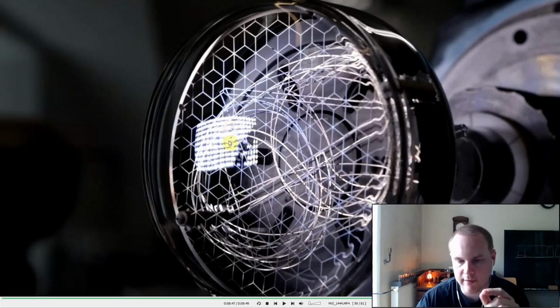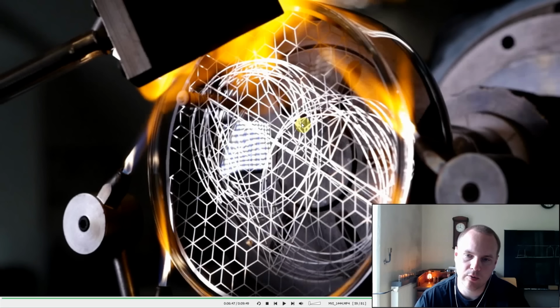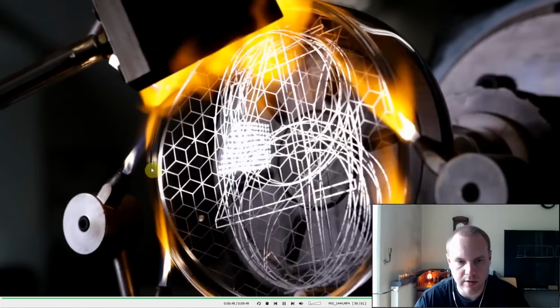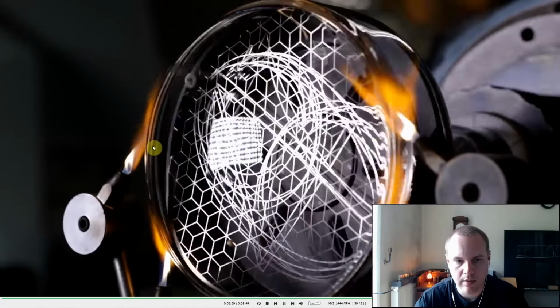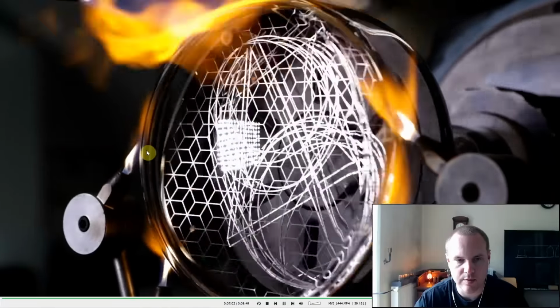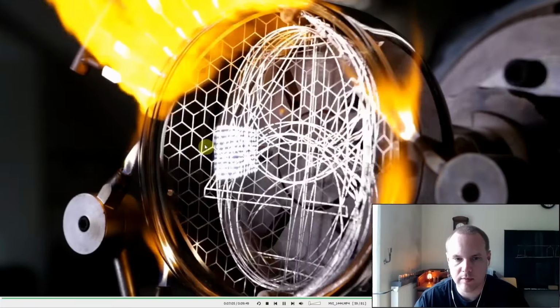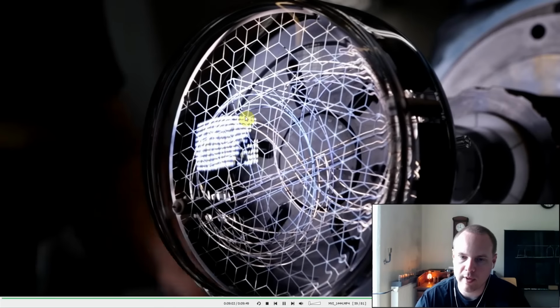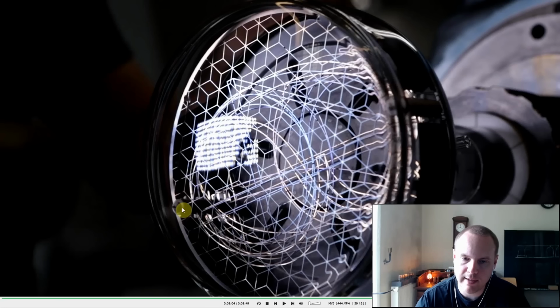The problem is that we didn't have the purging gas on during the annealing process, so the gas which is escaping from the torch could enter the tube and react with the digits. The reason why I had to close the purging gas was that it was creating overpressure inside, and the front windows started to lift from the envelope. You can see here. Here you can see how it's blowing. So this test was also not done well, but we can see that we can keep the digits shiny without oxidation during the sealing process, and then we need to focus more on the annealing.